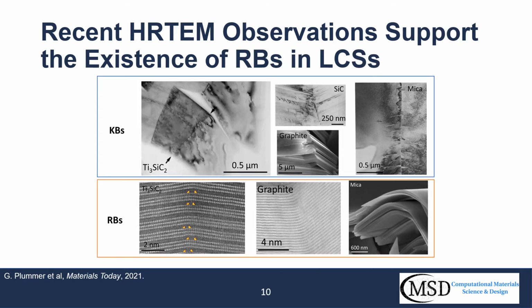So in agreement with the observations made here, recent high-res TEM images in layered crystalline solids, including MAX phases and graphite, do indeed indicate that the boundaries typically assumed to be atomically sharp classical kink boundaries at lower resolutions, as seen in the upper pane, are in fact likely ripplocation boundaries with curvature of the basal planes spread over several nanometers, as shown in the lower pane. We suspect additional work on other layered crystalline solids will serve to further confirm this idea.